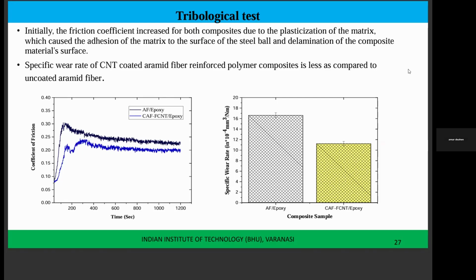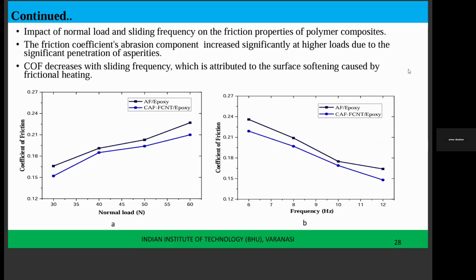Next slide, please. When we change the load, rather than keeping it at 30 newtons, if you increase the load to 40, 50, and 60 newtons, you can see a linear increase of the coefficient of friction because of asperities penetration. And the coefficient of friction decreases when you increase the number of cycles or frequency. This is because of the surface softening caused by frictional heating.